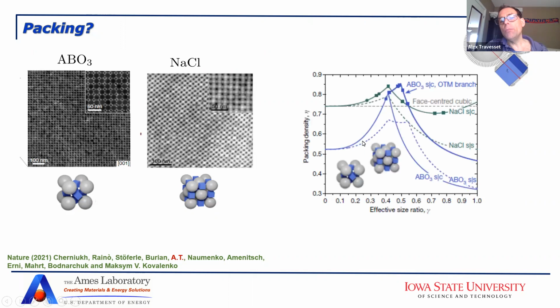And then when you compute the packing fraction, what you see is that in general, for hard spheres, it doesn't quite work. But when you include the presence of vertices, as you have here in the corners, as I already anticipated, then you see that the packing fraction is greatly enhanced, and therefore you can predict the lattice constant for these perovskites.